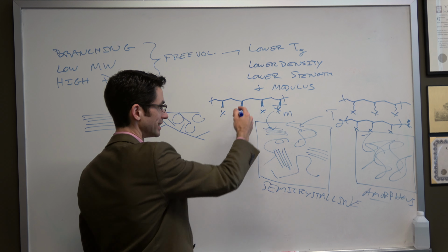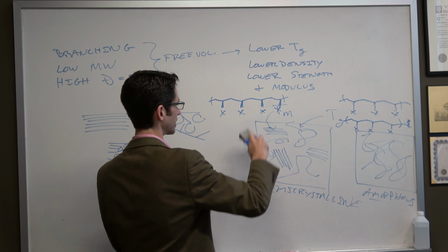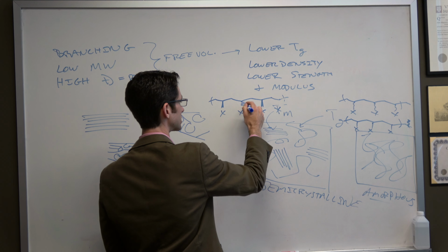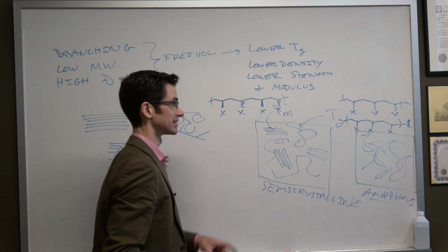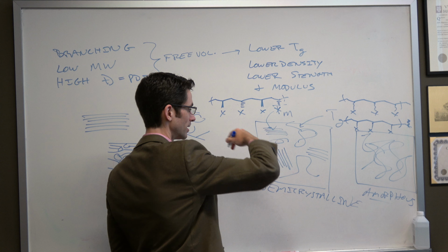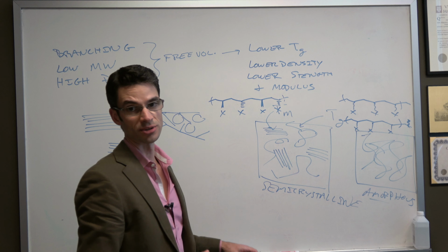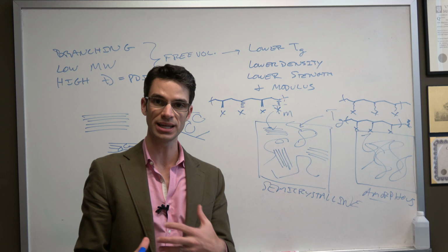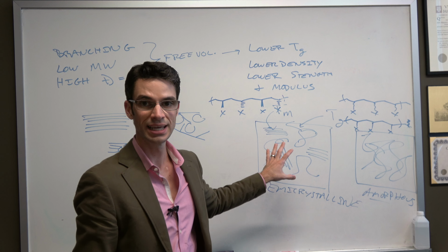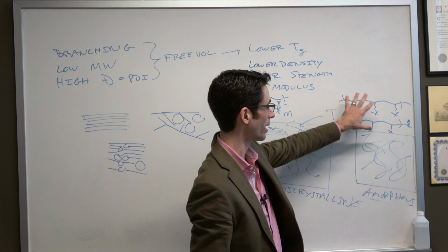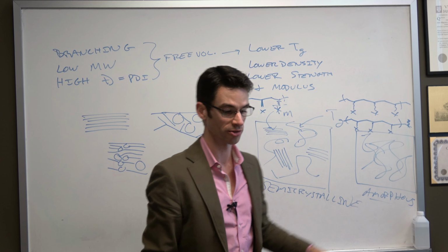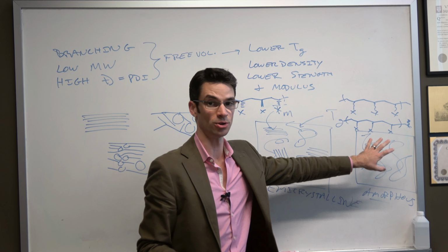And this is called isotactic. Or in the case where they point in opposite directions but alternating, this is called syndiotactic. Now, because you have regularity here, you're allowed to have crystallites. So if there's regularity, you can have the opportunity for crystallites. If there is randomness, then you don't get crystallites, you get a completely amorphous material. So no Tm here, only a Tg.